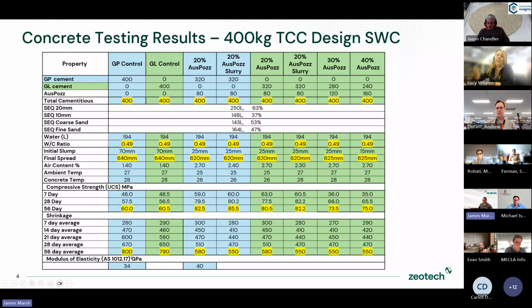And also shrinkage, around about 800 for both of the standard cement grades, but then dropped down right across the board to the 500s. So a very good reduction in shrinkage as well. And also we just did one test for modulus, and that was probably just a reflection of the increase in strength. There was also a fairly high jump in the modulus strength as well. So some very interesting results there.